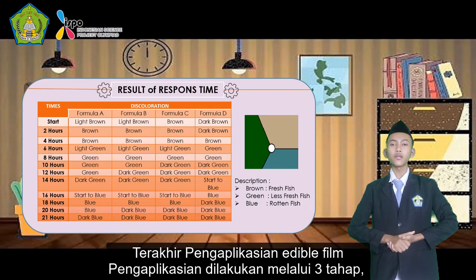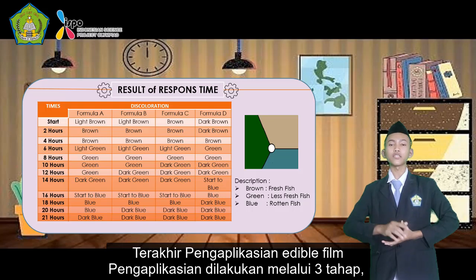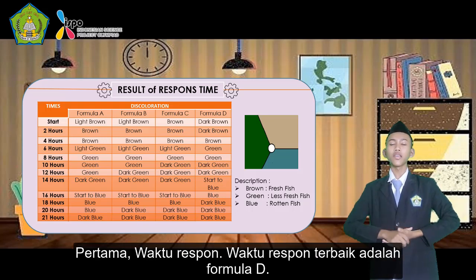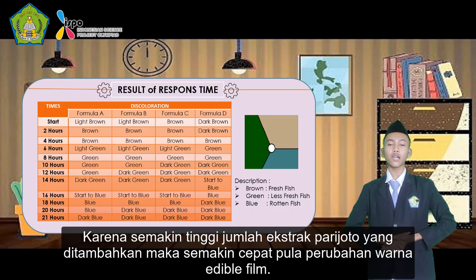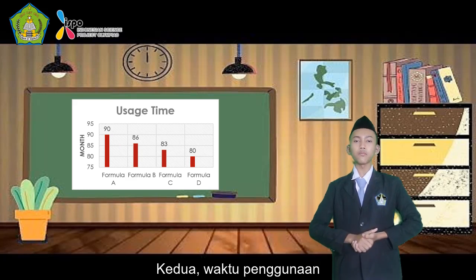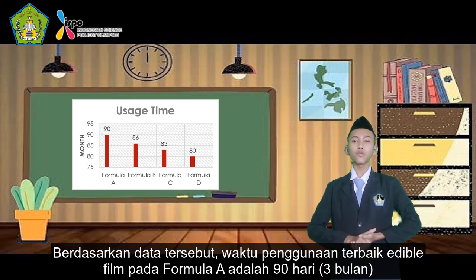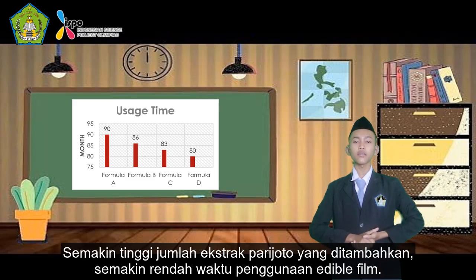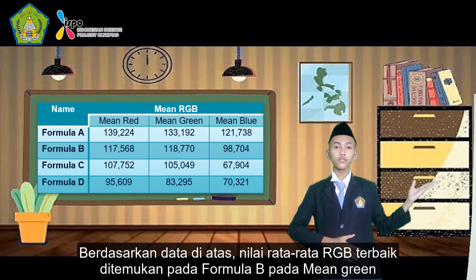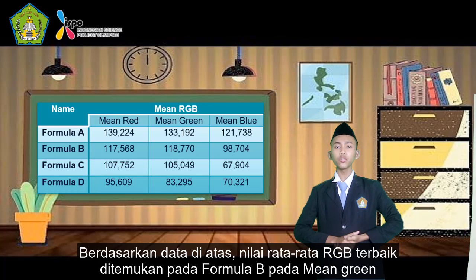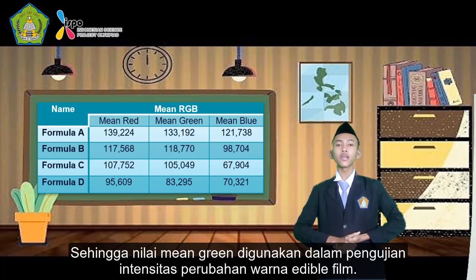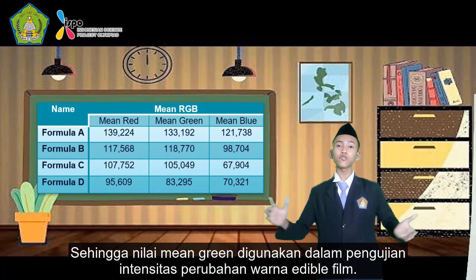The last, application of the edible film. The application was carried out in three stages. First, response time. Based on the data, the best response time of the edible film was formula D. The higher the amount of parichoto extract added, the faster the discoloration of the edible film. Second, the usage time. Based on the data, the best usage time of edible film in formula A was 90 days or 3 months. The higher the amount of parichoto extract added, the lower the usage time of the edible film. Third, the discoloration. Based on the data, the best RGB value was found in formula B at mean green. So, the mean green value is used in testing the intensity of discoloration of edible film.